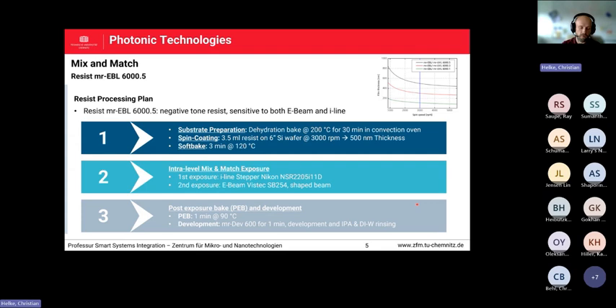And the whole lithography process is divided in 3 parts. The first one is the realization of the photoresist layer, meaning we start with a substrate preparation, meaning the dehydration bake for 30 minutes at 200 degrees Celsius. Then we perform the spin coating. Here the parameters are there. We spin coated it on 6-inch wafers at 3000 rounds per minute, so that we receive here the 500 nanometer resist thickness, as you can see it here and in the scheme. And then we did the soft bake, 3 minutes at 120 degrees Celsius.